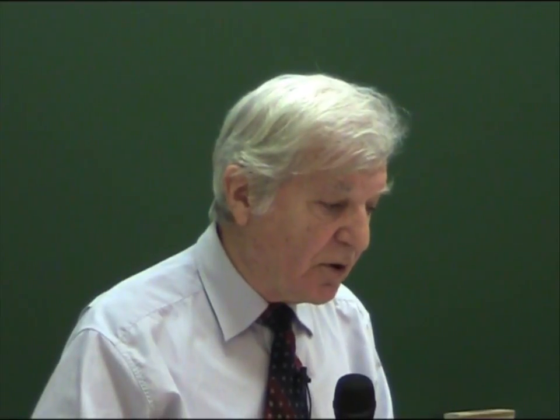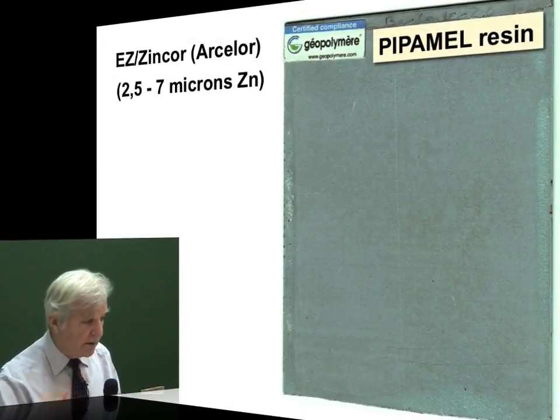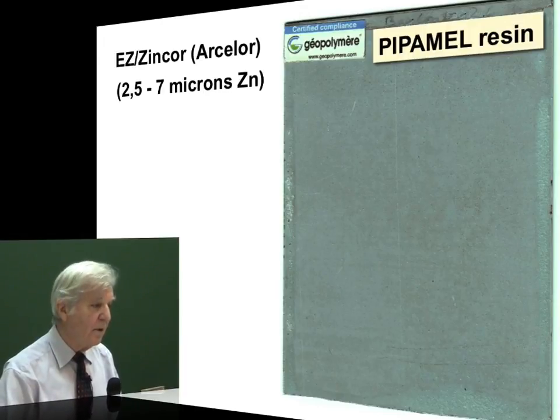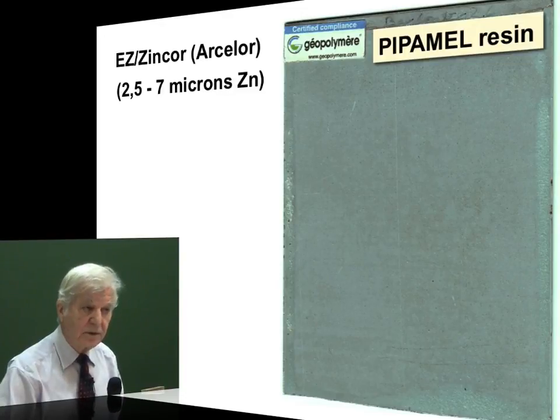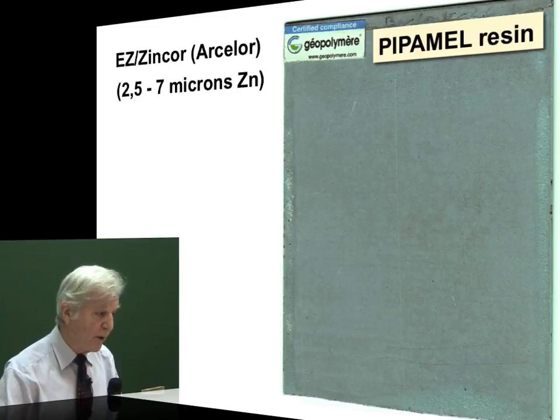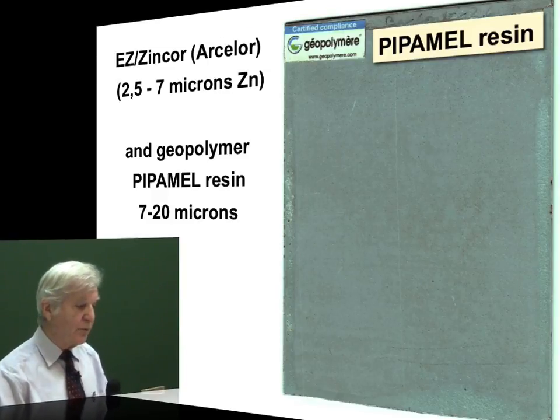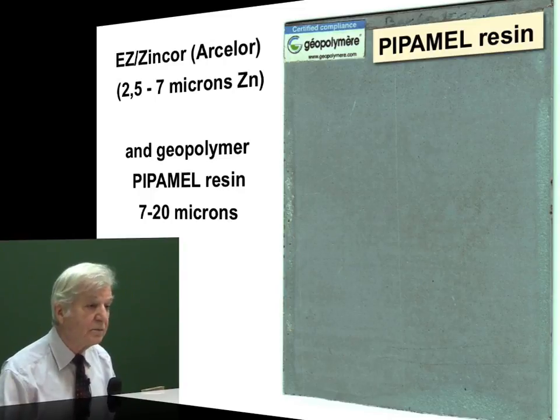Because talking on working on steel, it is well known from the steel processing or manufacturing industry for coating that a metal like zinc plays a very important role in terms of adhesion. And we had a project that has been run for 3 years, and we applied on these special called Zincor steel, a very special geopolymer resin, very fine, 2.5 to 7 micron. No, this is the thickness of the zinc coating. We applied what we call the geopolymer Pipamel resin, 7 to 20 micron thickness.